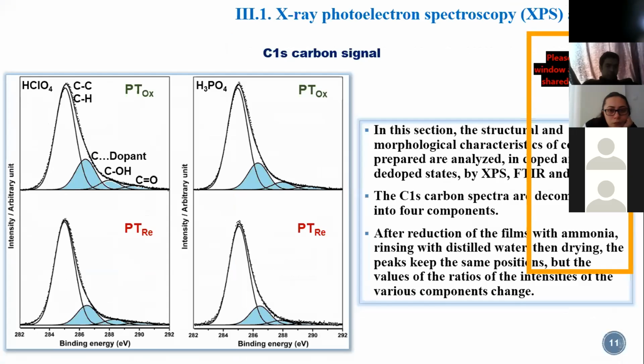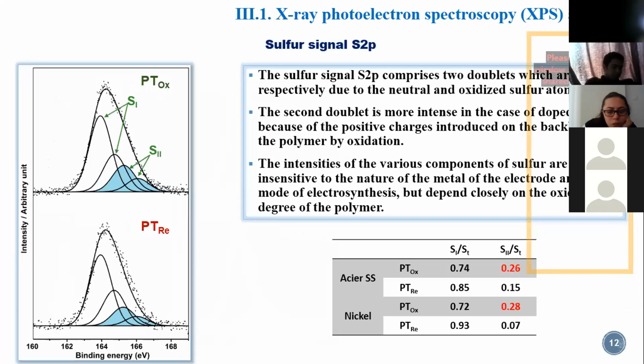In this section, structural and morphological characteristics of the prepared coatings are analyzed. The carbon spectra are decomposed into 4 components. After reduction, the peaks kept the same position, but the value of the ratio changed. The sulfur 2p doublets are respectively due to the neutral and oxidized sulfur. The second doublet is more intense in the case of doped film because of the positive charge induced in the backbone of the polymer by oxidation. The intensities of the various components of sulfur are insensitive to the nature of the metal, and the mode of electrosynthesis, but depend closely on the oxidation degree of the polymer.